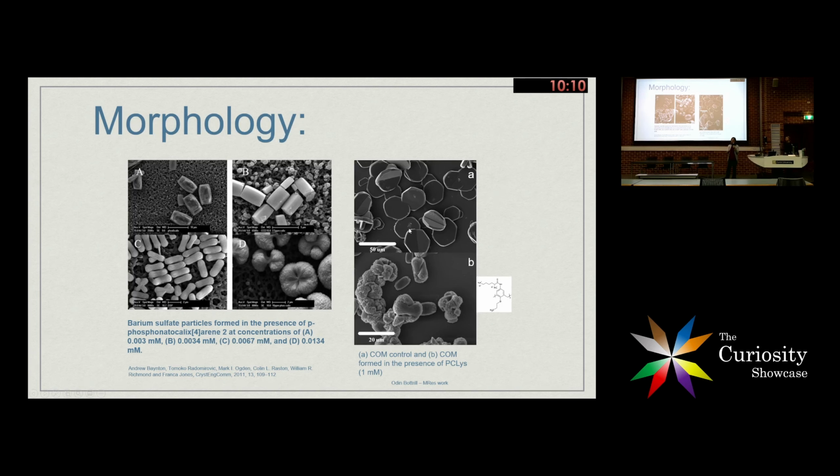Similarly, in this case, you've got calcium oxalate monohydrate. In the presence of this calixarene-containing lysine, pardon me, you get these particles. You can do Raman and you can confirm that this is still calcium oxalate monohydrate, but the shape and size has been dramatically altered in the presence of this particular molecule.